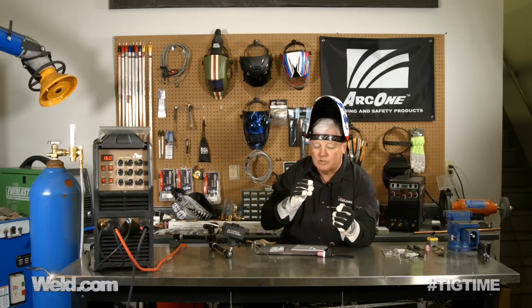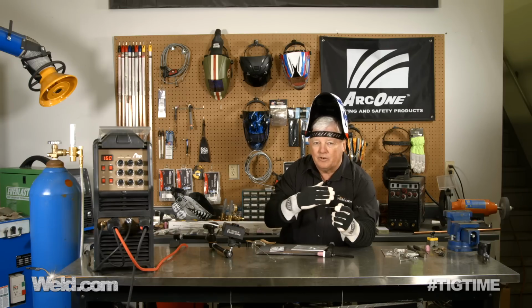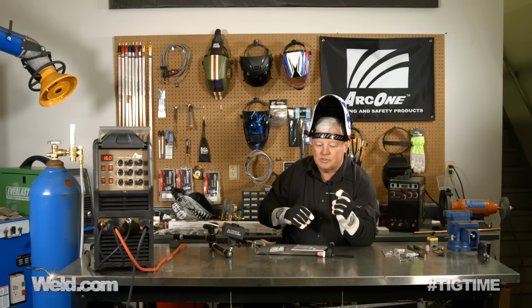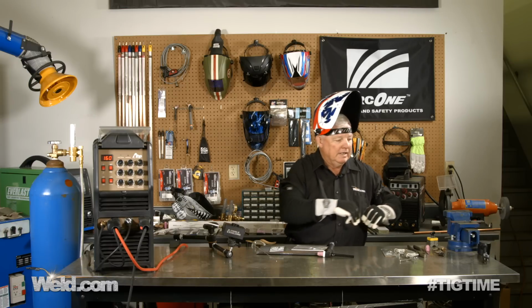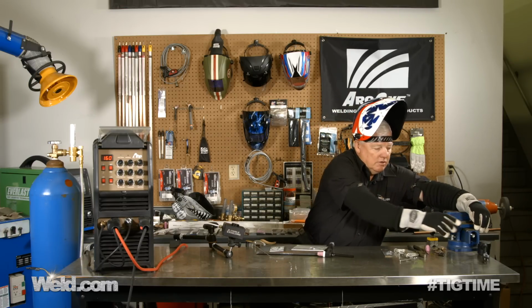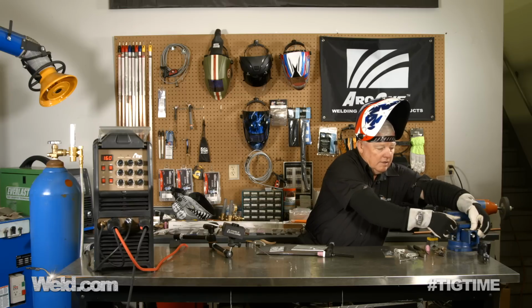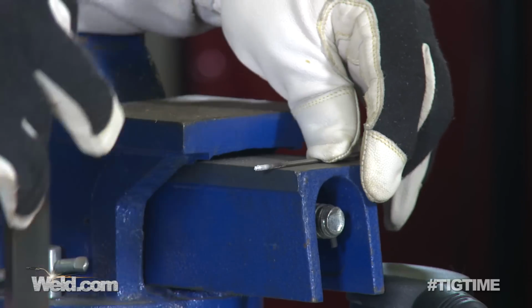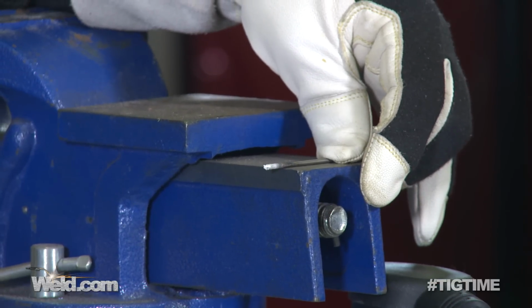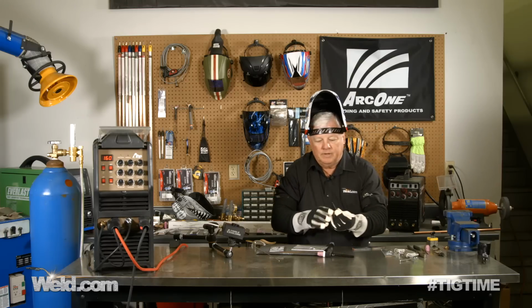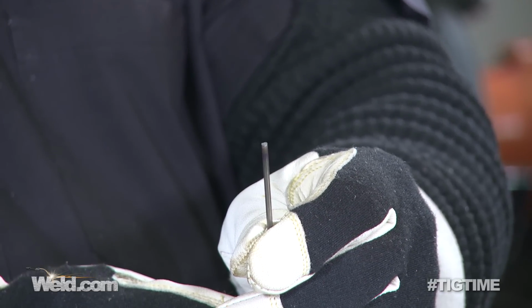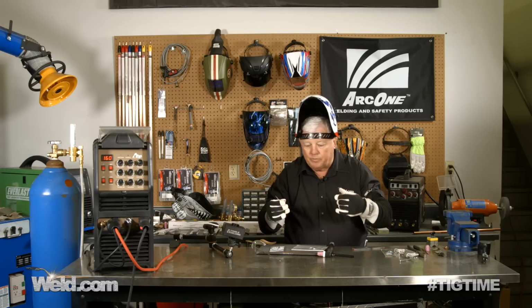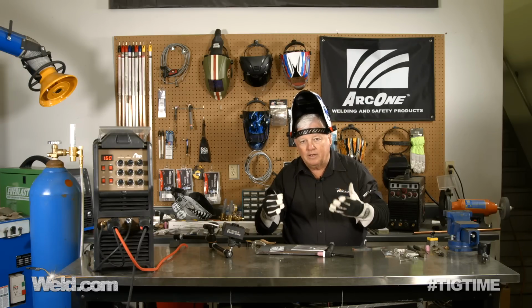And when I say break it off, it needs to be snapped off very quickly. Tungsten will have a tendency to splinter if you're too slow with the breaking process. So watch what I do. I find a sharp edge like this vise here. And you can use any sharp edge. You can use any material. Okay, so I've broken off the bad part of all this. Now I'll regrind, I'll put a point on it, and then I'll reestablish an arc, and I'll show you how well it cleans up.